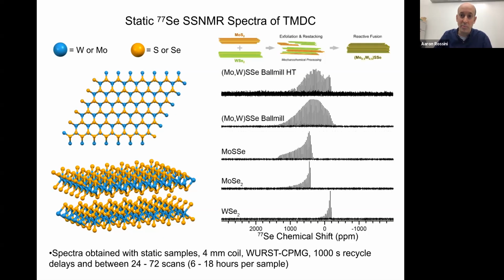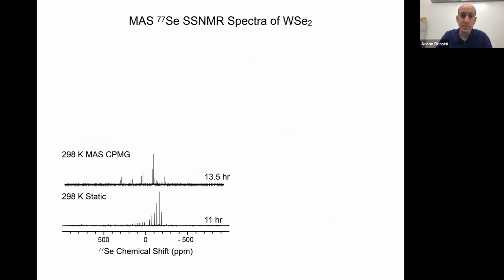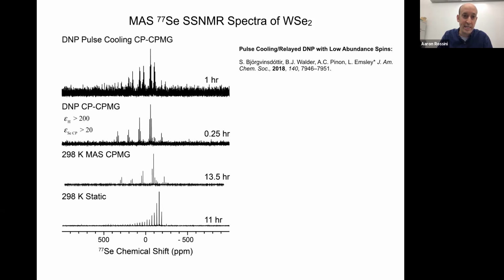Now, some of these spectra are rather broad, and we'd like to try and get high resolution spectra to give us a more accurate picture of the metal distribution during the milling step. And so we tried to do some MAS experiments to get the resolution up. So this is shown for the tungsten selenide here. So we can get that static spectrum in about 11 hours with CPMG. We can also do CPMG acquisition under MAS conditions, and we can obtain a magic angle spinning spectrum in about 14 hours. The long experiment times required for room temperature NMR prompted us to try DNP.